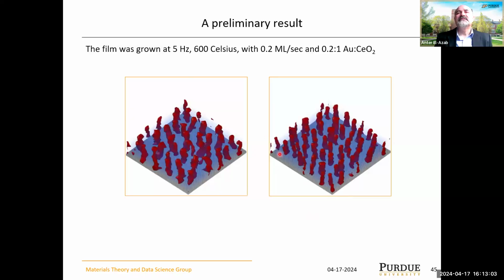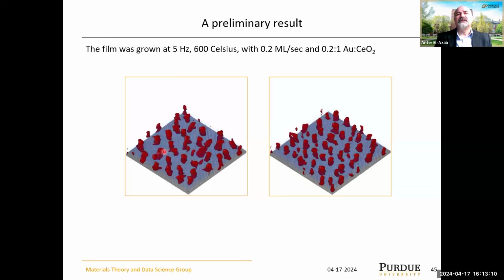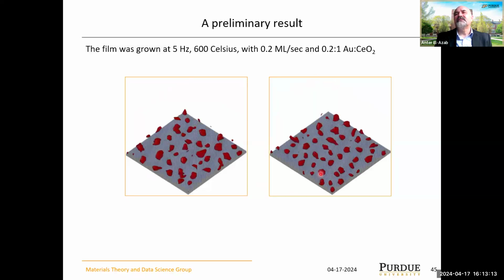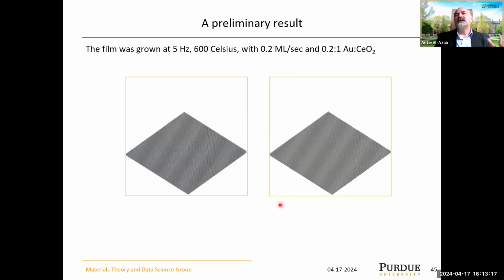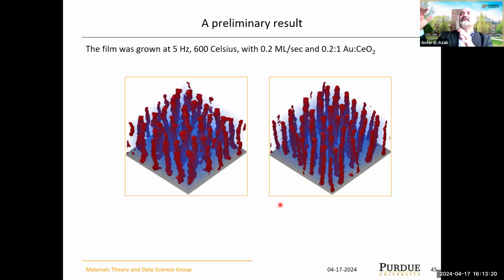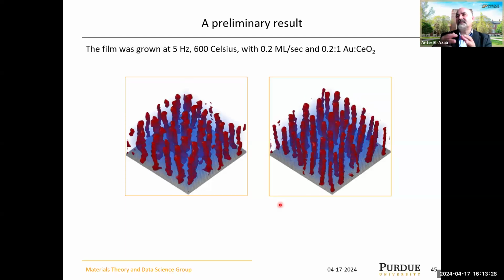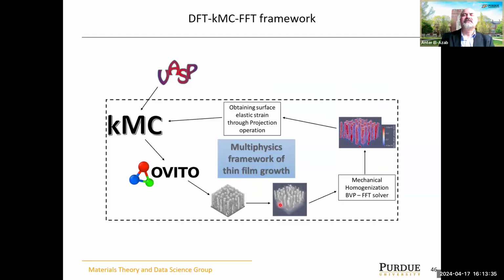And we did discover that there is an impact on the shape of the pillar. You see here a lot of roughness on the pillar surface, but these pillars on this side here are actually more straight. Right now, he's in the process of integrating all that DFT into the Kinetic Monte Carlo, the elastic solver, the DFT parameterization, and the KMC techniques together. That brings me to my final view graph here for this framework. It works nicely for understanding the kinetics of this growth. It is being enhanced currently with the elastic solutions and DFT parameterization that depends on the strain and so on.